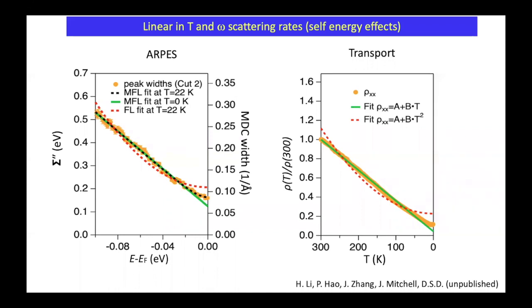And I fit this to either a Fermi liquid type of analysis, which doesn't do such a great job. Marginal Fermi liquid at zero temperature would be perfectly linear, but I'm at finite temperature, I'm at 22K. And that is the black dashed lines, which fit quite nicely. So sort of a linear thing here, and quadratic-like if you like, but really just marginal Fermi liquid all the way. And here's transport data, normalized resistance versus temperature.